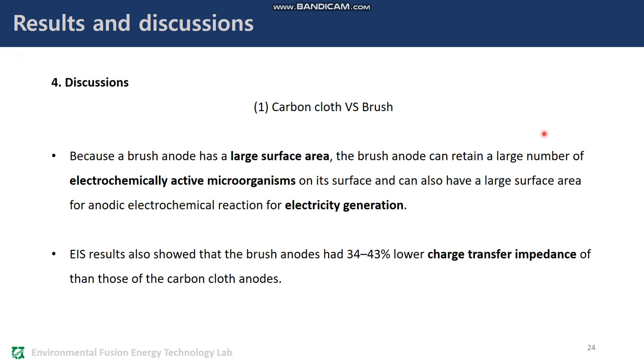Discussions. First, we compared carbon cloth and brush in terms of anode material. Because a brush anode has a large surface area, the brush anode can retain a large number of electrochemically active microorganisms on its surface. It can also have a large surface area for anodic electrochemical reaction, for electricity generation. EIS results also showed that the brush anodes had 34 to 43% lower charge transfer impedance than those of the carbon cloth anodes.